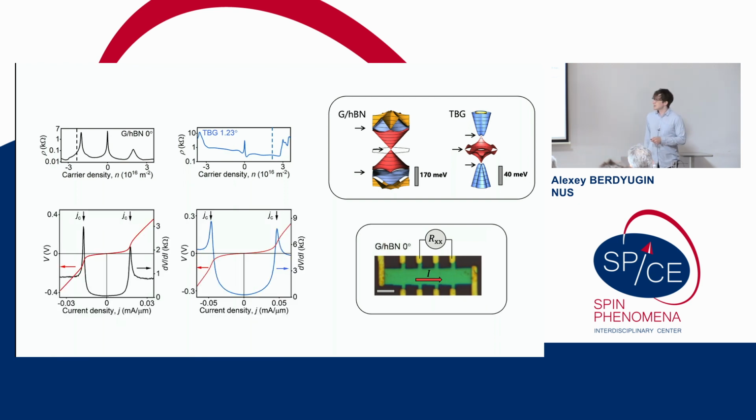And the result immediately got our attention for several reasons. In red, in those plots, you can see the IV curves, and in blue and black you can see the corresponding differential resistivity, which is simply the derivative of those IV curves. If you look at this IV curve, it closely resembles a superconducting transition.